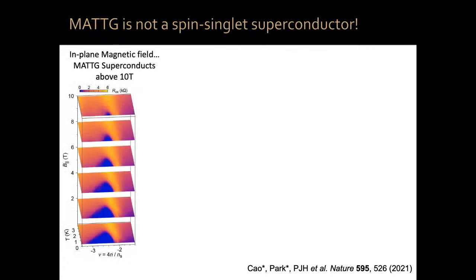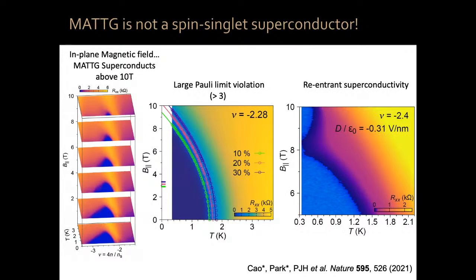Now, what we have discovered in magic angle twisted trilayer graphene, I'm just going to flash it, not give any details, is that this system violates this Pauli limit by a huge factor. If you measure the resistivity, this is the region of superconductivity. Resistivity versus temperature and parallel magnetic field. Superconductivity should disappear at this value, but you can see it stays superconducting at much higher values.